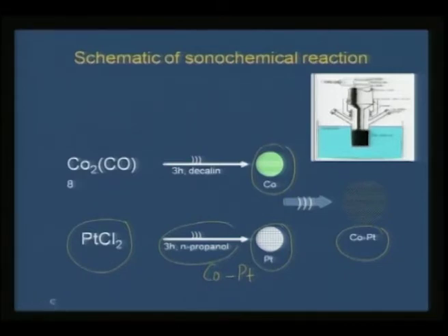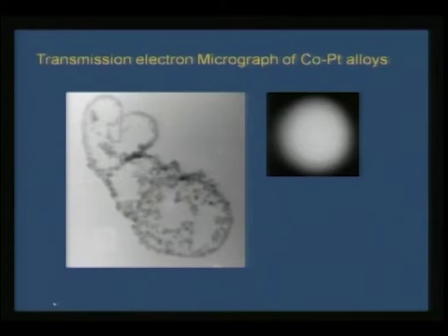And some of the view graphs will tell us what sort of product we can get. This is a typical transmission electron micrograph of the cobalt platinum nanoparticles that are formed. You can see they are making some sort of heart shaped decorations, and essentially each one of these small dots is a cobalt platinum nanoparticle, roughly of the order of 2 to 3 nanometers in size. How do I know that? If you take the selected area diffraction of this particular compound, it gives a blurred image, which means it is not even polycrystalline, it is really in amorphous form. So you do not get any electron diffraction spots.